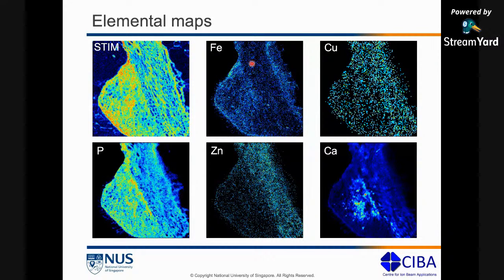If you compare iron and zinc, you can clearly see the complementary effect. Where you have less iron, you have more zinc. Where you have less zinc, you have more iron. This is what I meant when I said that off-axis STIM imaging gives you elemental contrast. Off-axis also gives you the advantage of preserving your detector for a longer time; it increases your detector lifetime. At the same time, you also have this distinct advantage of getting elemental contrast. So that's one of the reasons why we try to stick to off-axis STIM imaging as much as possible.